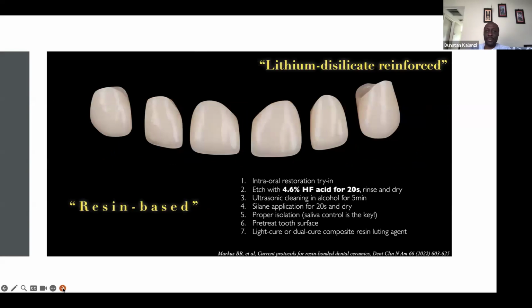The same would apply with your lithium disilicate. But here you're using hydrofluoric acid of 4.6%. Sometimes it doesn't matter. You might just use 8, but this is done by the lab. Mostly it's done by the lab for you.